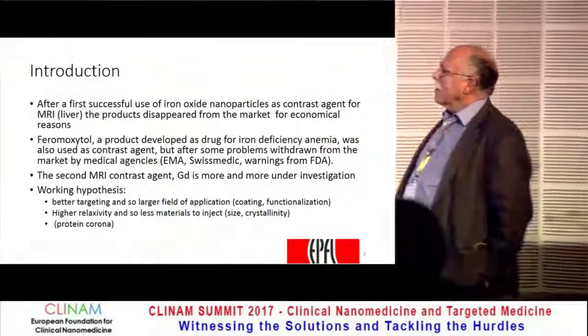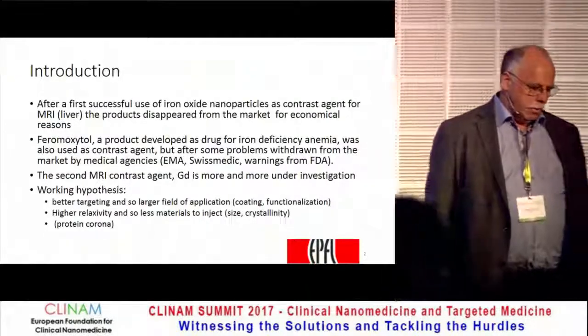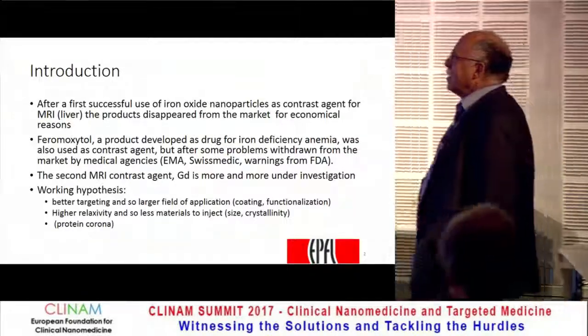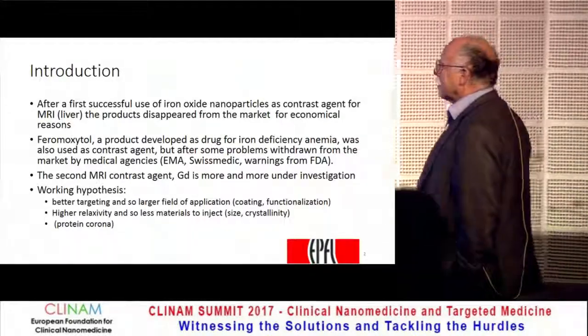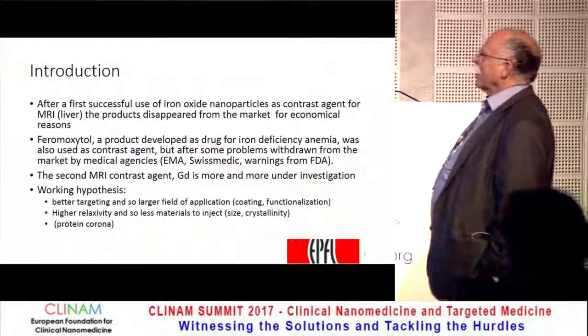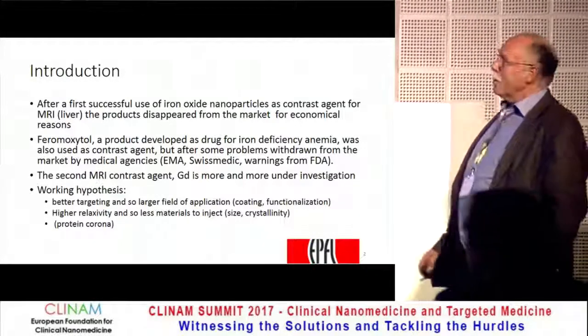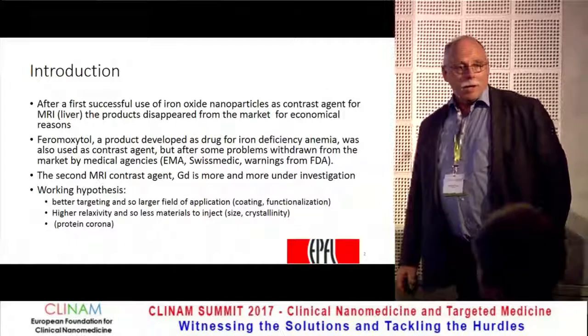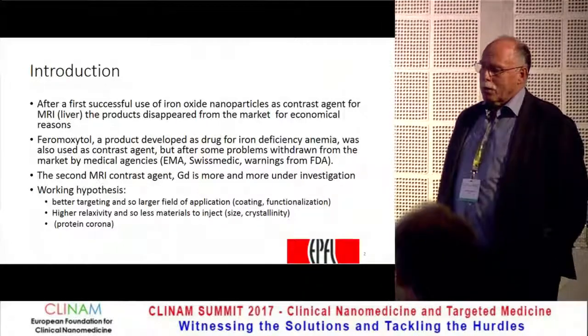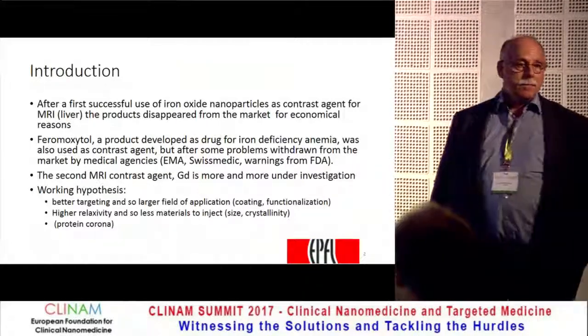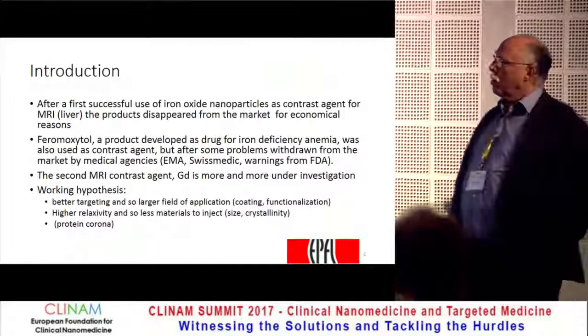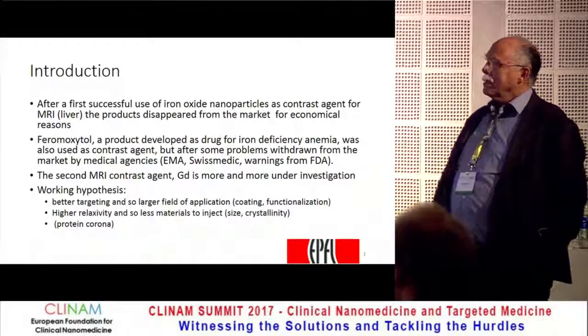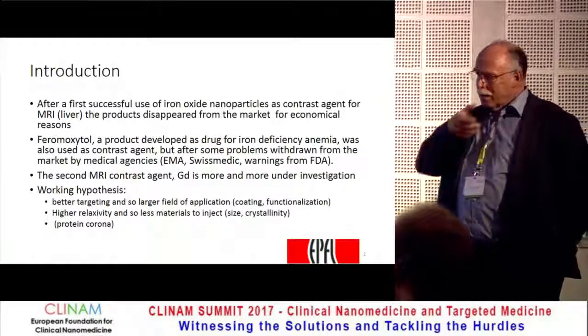First, I'd like to say this is not new. Everybody knows that iron oxide has been used for a long time, 10 years or more, as a contrast agent for MRI, especially for the liver. Now this product is disappearing from the market, especially for economical reasons, because the market was too small, and it's only applicable more or less in the liver, in the healthy part of the liver.